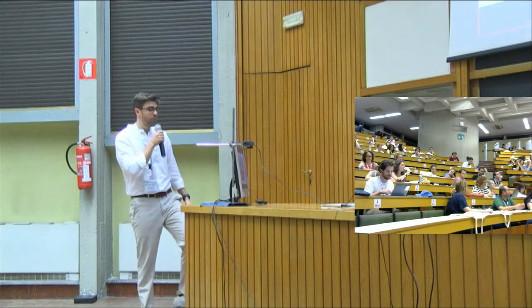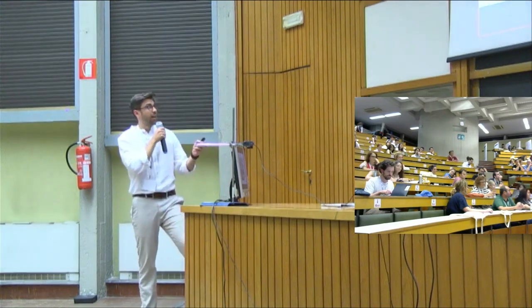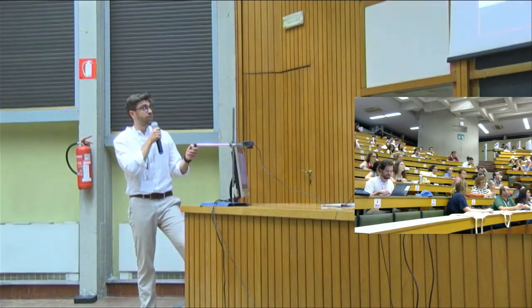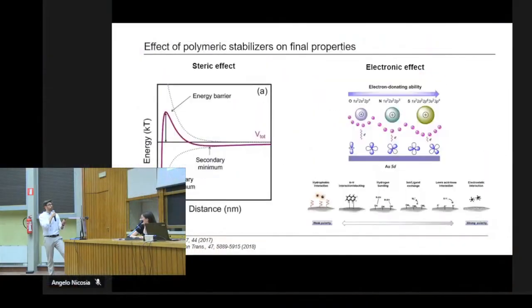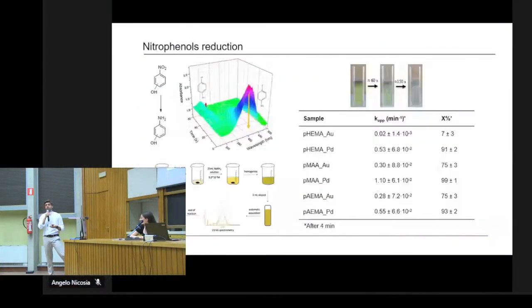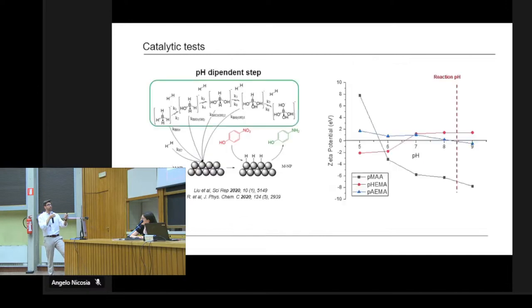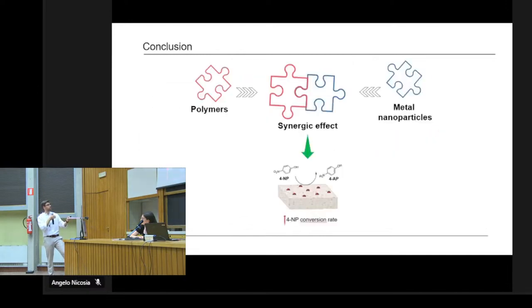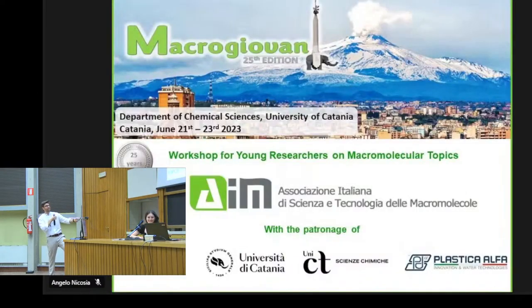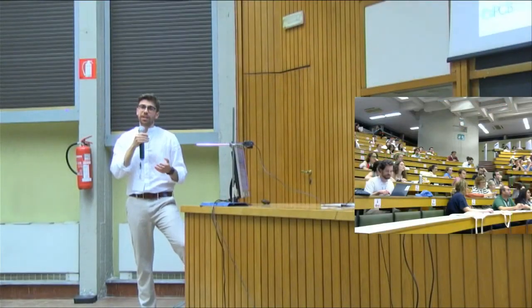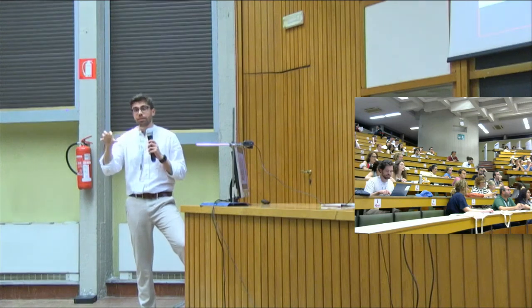Good point. We have a problem evaluating the porosity of the system. To carry out the BET analysis, it's necessary to have a sample with high density. But this type of cryogel has a very low density, so it's difficult to analyze, and we need to use indirect methodology.